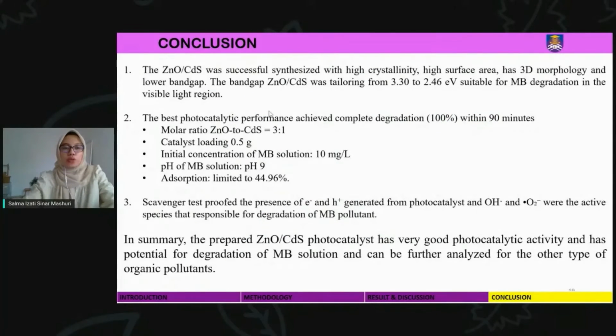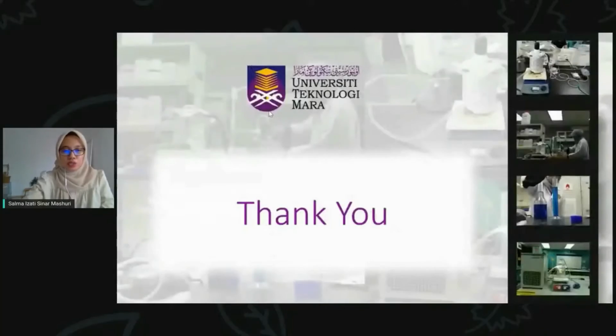So as a conclusion, we can use zinc oxide cadmium sulfide because it has high crystallinity, high surface area, 3D morphology and lower band gap. Okay, the best photocatalytic performance that can be achieved is 100% within 90 minutes. So the scavenger test proved the presence of electron and hole generated from the photocatalyst, meanwhile hydroxyl radical and superoxide were the active species responsible to degrade methylene blue. So zinc oxide cadmium sulfide is a promising photocatalyst in degrading methylene blue solution and can be further analyzed for other types of organic pollutants. So thank you.